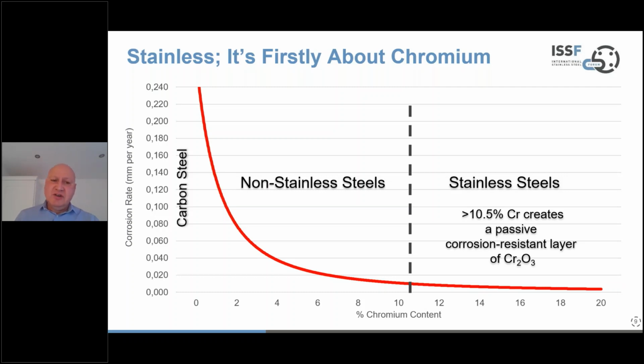So on the left, with very low chromium content, you have carbon steels. To the right of the almost vertical red line in the early part of the chart, before the dotted vertical line, you have the non-stainless, the alloy steel category. And then when you get to 10.5% chromium and more, you're into the family of stainless steels. And stainless is stainless, as many people know, because of the passive or corrosion resistant layer of chromium oxide on the surface, which we'll take a look at in a moment. So chromium is one of the really important elements in making stainless steel corrosion resistant.